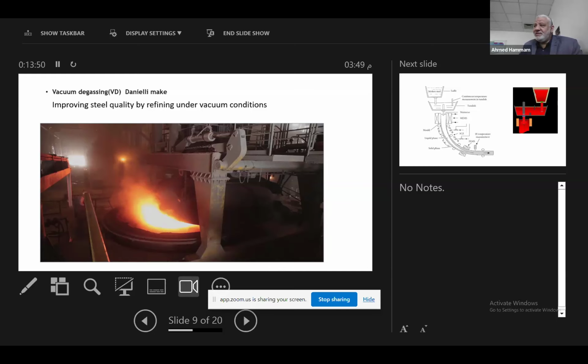Then we ensure that the material has reached a level of gases suitable for casting to get the desired quality. Samples should be taken from each stage: from the ladle furnace, from the vacuum degassing, from the ladle. At every stage we have to ensure that samples are taken and the results are according to standards.